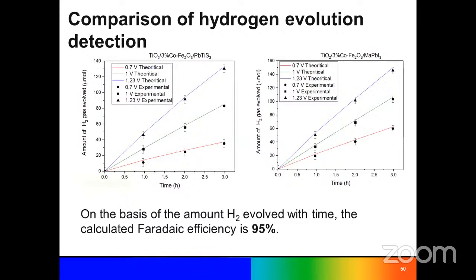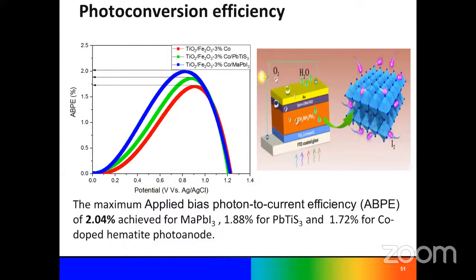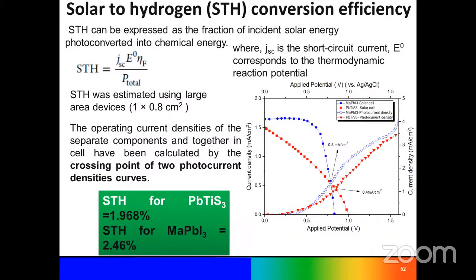Then we check the amount of hydrogen we produced. In this case, we got around 95% efficiency for the 3% cobalt doped hematite coated with methylammonium lead iodide. Finally, the applied bias photocurrent response reached around 2.04%, whereas it was initially 1.8. After coating with this perovskite material it reached 2.04% efficiency. Then we checked the solar to hydrogen efficiency, and with methylammonium lead iodide we got 2.46% solar to hydrogen conversion efficiency.